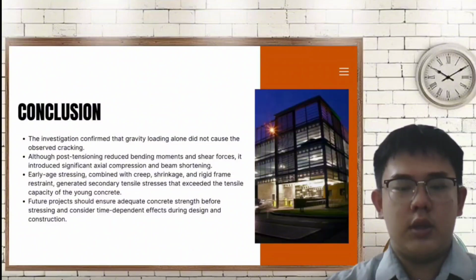Although post-tensioning successfully reduced bending moment and shear force, it also introduced significant axial compression and beam shortening. When stressing was carried out at an early age, the combined effect of creep, shrinkage, and restraint from the surrounding frame generated secondary tensile stress. This tensile stress added to the tensile stress in the young concrete, leading to the development of cracks. Therefore, future projects should ensure that concrete has achieved sufficient strength before pre-stressing begins. Designers should also consider time-dependent effects such as creep and shrinkage during both the design and construction stages to minimize the risk of similar cracking.